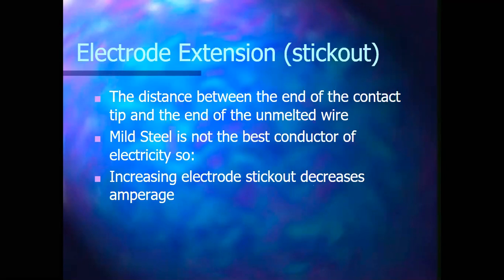But when we were welding, some of us were far away from the plate and we were getting that pop, pop, pop, pop kind of thing, and little chunks of red hot wire were breaking off. That is because we don't have enough amperage to fully burn off the wire when we're welding. But when I was working with some of you, I grabbed the end of your welder and jammed it in there nice and close to the weld. That reduces the amount of resistance through the distance on the electrode wire, and then we can transfer that to the plate. So we get a much better weld with shorter stick out distance.